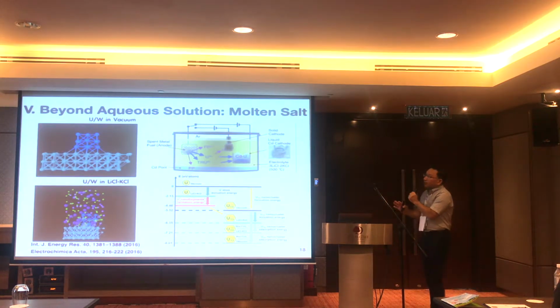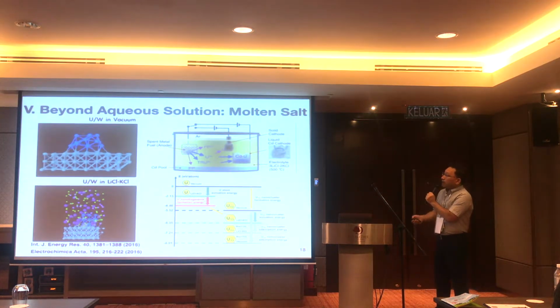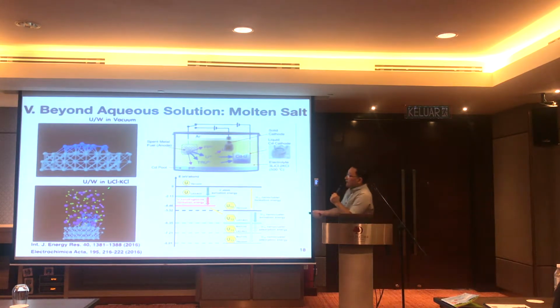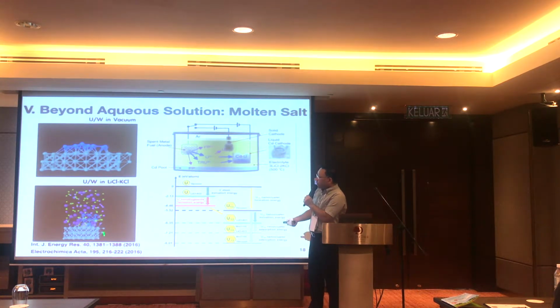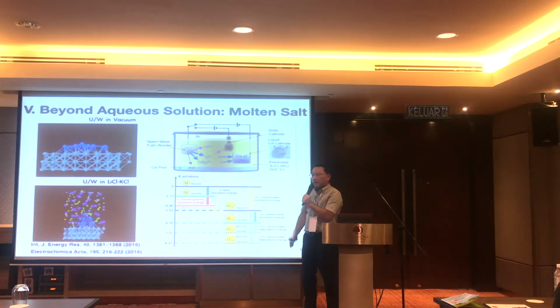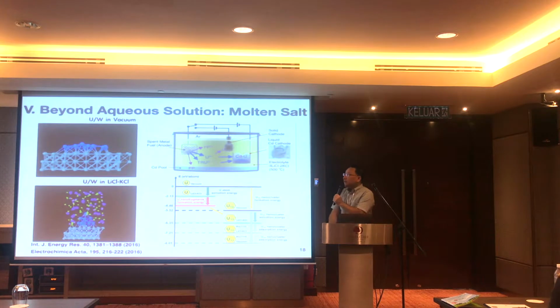You're going to see two different pictures here. The first one is the tungsten electrode and uranium nanoparticles, and how they form the morphology. They form a flat, monolayer, layer-by-layer structure. How about in vacuum conditions? How about in molten salt conditions? You see that the topology is very different. Uranium in molten salt, where green is actually chloride, grows in dendrite form, not the flat type.